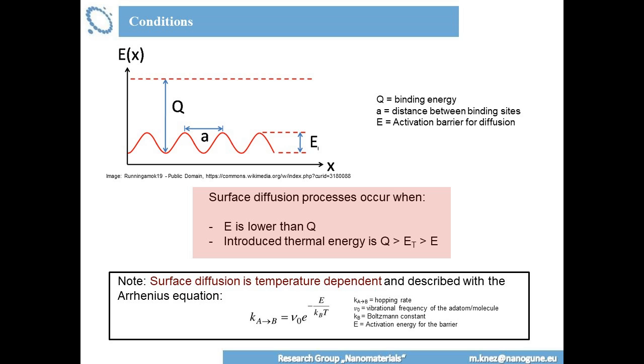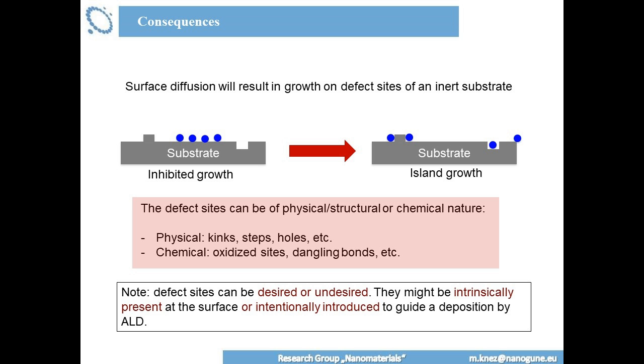This diffusion is temperature dependent, and here the Arrhenius equation is the base principle for the temperature dependence of those hopping events. I think this is not really so important. This is just for you to have in mind. What is important is to know that you have a physical binding of molecules there. Typically they will desorb, but in some cases, if you have defect sites, they will also grow.